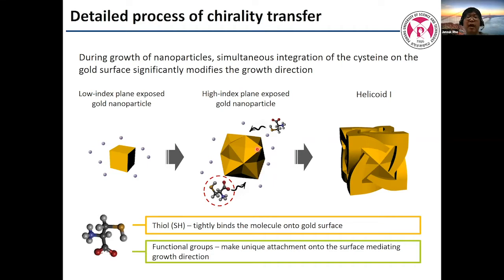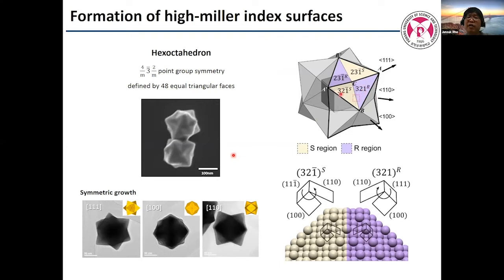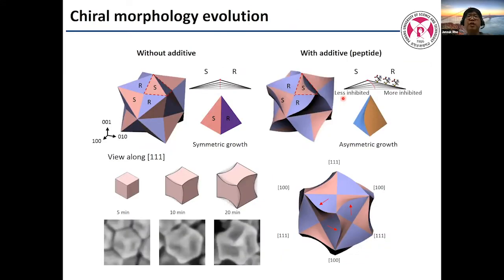So this cysteine has limited binding to the high Miller index planes, not the low Miller index planes. These are 111, 100, 110, but this is a 321 high Miller index plane. So this is basic 321 R, 321 L, and left-handed amino acid binds here, right-handed amino acid binds here. So they interactively change the growing direction. It's like curling counterclockwise here. Without this amino acid, they just grow in the 111 direction symmetrically. But in this case, the direction gradually changes and grows this way. So eventually we see such a helical shape in the gold nanoparticle.